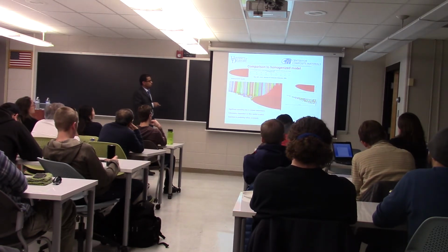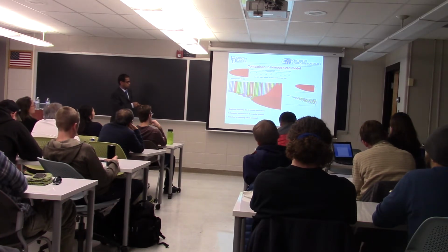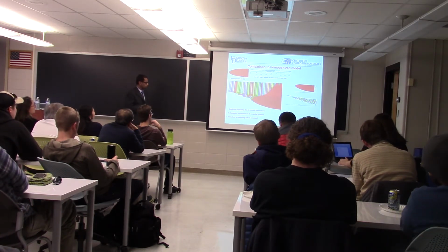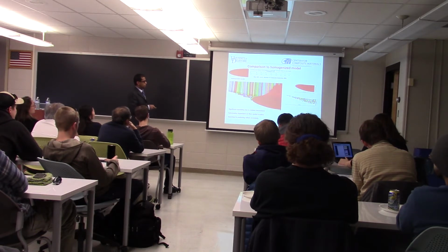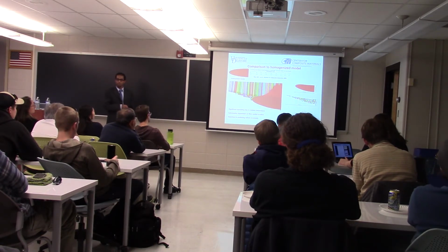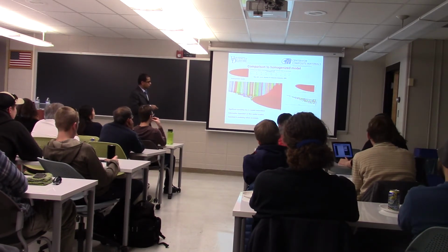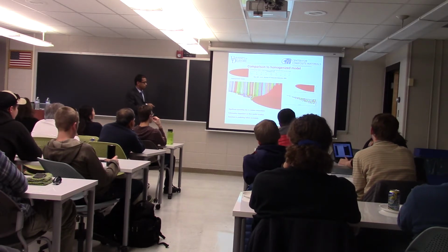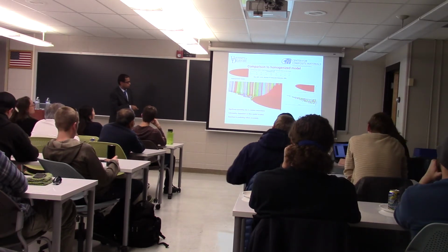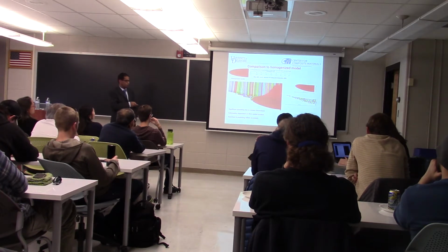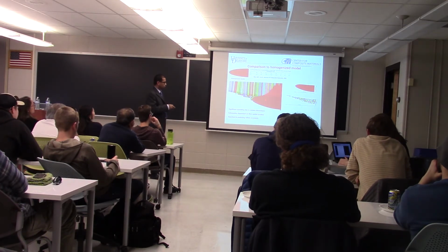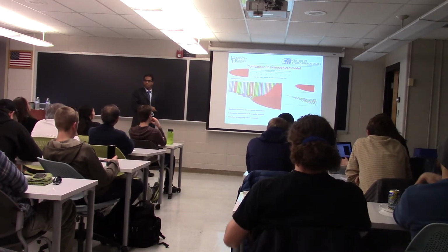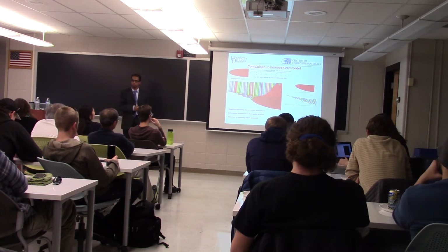So now, when you compare this response with the homogenized model, the major difference is in terms of dynamic fiber kinematics. The fiber length scale model predicts significant fiber spreading due to fiber-fiber contact interactions, whereas the homogenized model is not able to capture that deformation of the fibers and the progressive nature of loading and failure of these fibers within a single yarn.